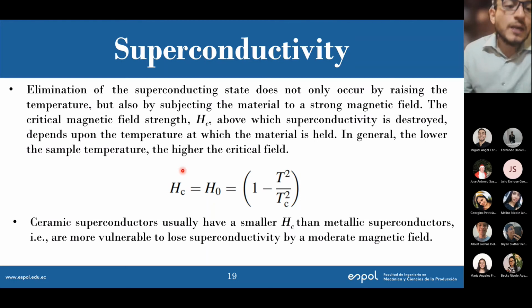So that's the critical magnetic field strength above which I lose superconductivity in a material. But this critical magnetic field strength depends on temperature. In general, if you see this equation, the lower the sample temperature, the higher the critical field. If the temperature is lower, I have a higher critical field. And this is the important thing.